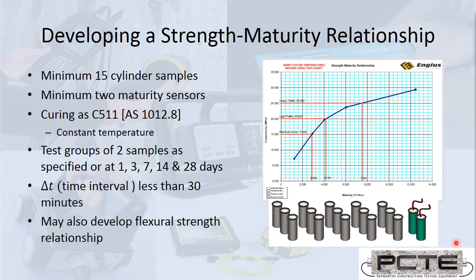If we don't have a particular schedule, the standard recommends 1, 3, 7, 14 and 28 days, but the choice of when the samples are broken is going to depend upon when it's important that the strength be gained. So if we're concerned with really early strengths, the first 5, 10, 15 MPa of strength gain, there needs to be lots of breaks early on. Whereas if we're concerned with mid-age strength, then 1, 3, 7, 14, 28 may be more suitable.